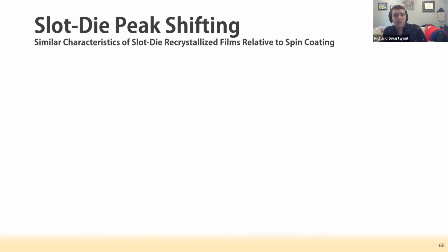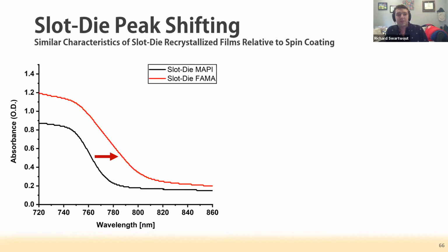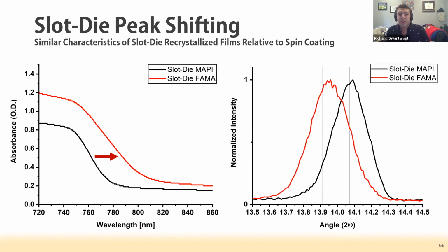Similarly to small scale, we see similar peak shifting on a large area of films, both in the absorption onset as well as in XRD peaks. These peaks also correlate with that quarter degree shift to higher angles, as we see in small scale, and they actually align as well to the small area peaks.